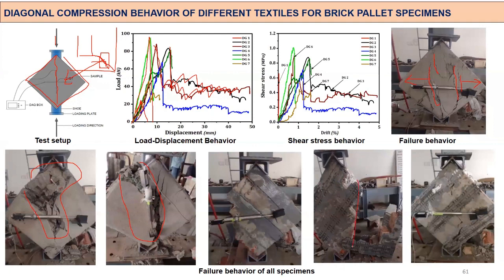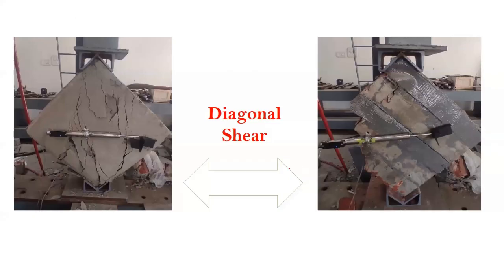So what happened exactly, this connection region completely gone off, and this is the corner region and completely came off. So with reference to the strength, if the strength of my textile is very less, I can only get the middle crack, and it is fair enough to resist the diagonal force. So when I'm using textile, I can get a behavior like this. When I use the same textile in a bonded way like this, I can get a failure like this.